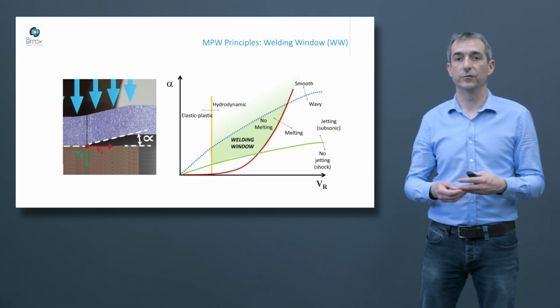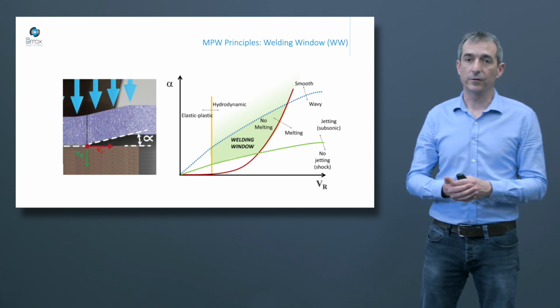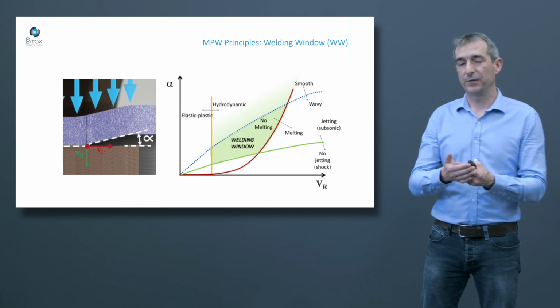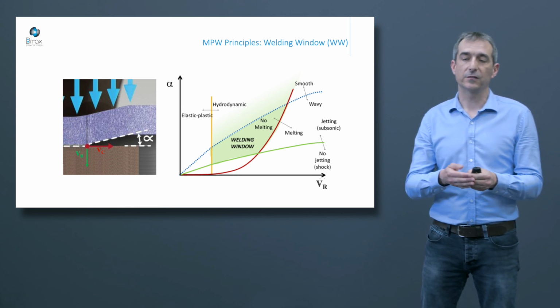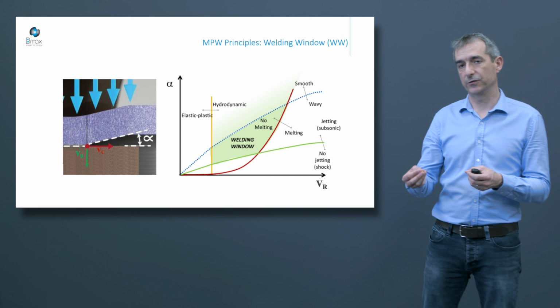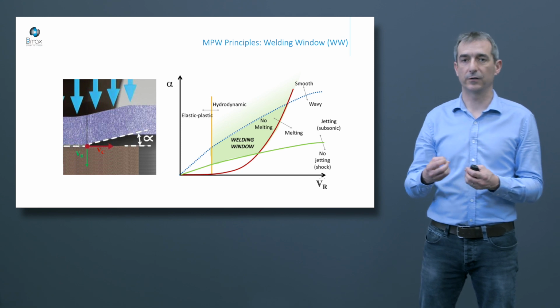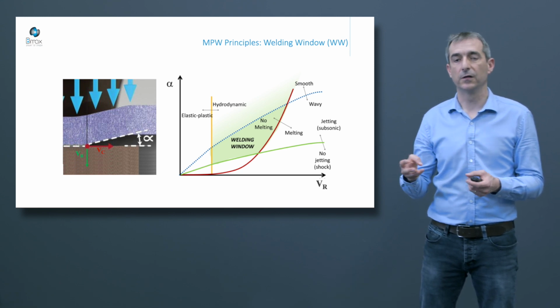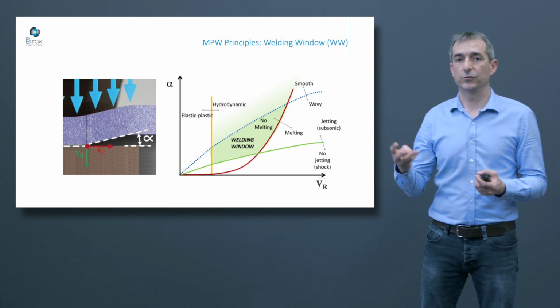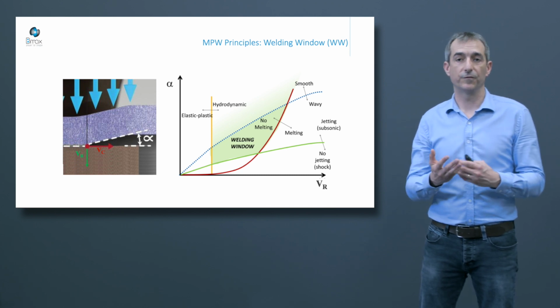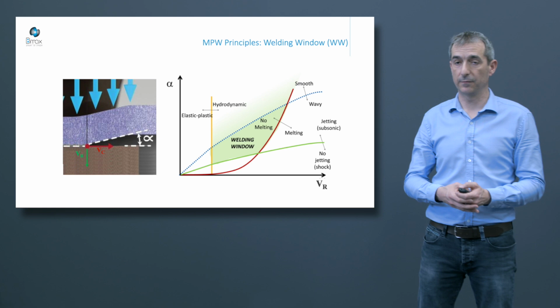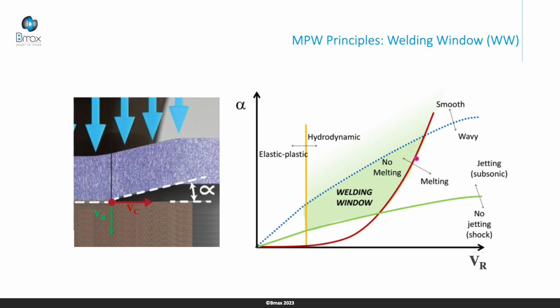The third is the melting temperature. When we have the speed at the impact, we can define the pressure and the temperature. And we have to be sure the temperature doesn't reach the melting temperature. If we reach this temperature, we have fusion and we change phase, and it's not solid, it becomes liquid. So this third line describes the theoretical welding window.